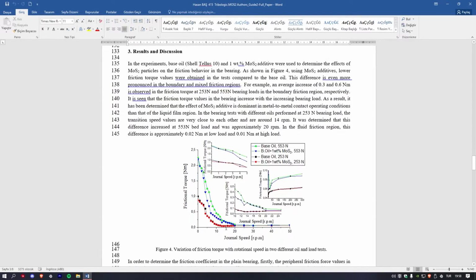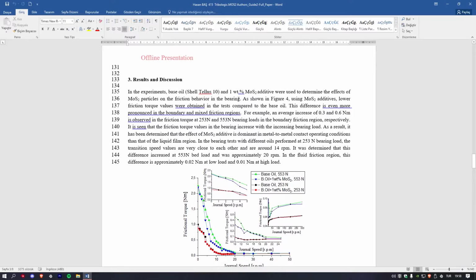It's seen in figure 4. As shown in figure 4, using molybdenum disulfide additives, lower friction torque values were obtained in the test compared to the base oil. This difference is even more pronounced in boundary and mixed friction regions.